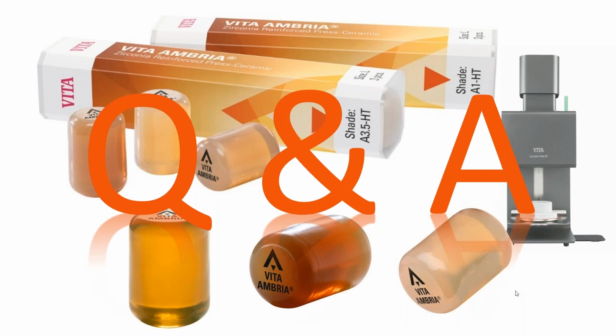get that fracturing. When it comes to the milling part, if it's a Celtra Duo that's milled, primarily you have to go through a glazed tempering process to reduce the milling striations, all those milling grooves that are now milled into the material, and that'll cause the fracturing.